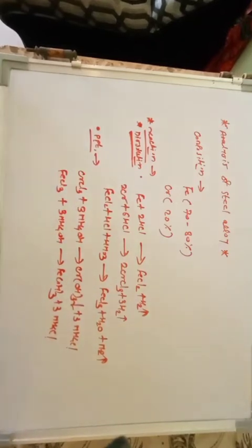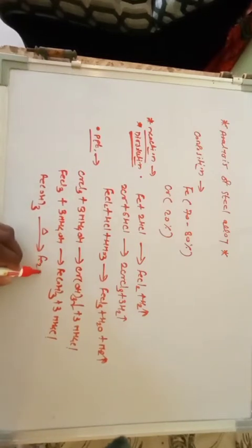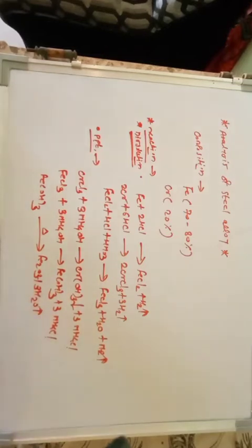So after dissolution, the chlorides of chromium and Fe react with ammonium hydroxide, and there is a formation of their hydroxides as a precipitate, chromium hydroxide and iron hydroxide. This iron hydroxide Fe(OH)3, on heating, is converted into Fe2O3 plus 3 water molecules. So it will be weighed as Fe2O3, and from that we can find out the percentage of Fe. Now let us discuss the chromium.